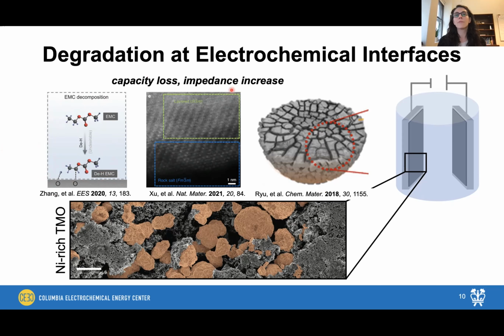We also have a transition from the layered architecture within the active particles to this rock salt-like structure on the surface of the NMC811 that leads to this increased resistance during extended electrochemical cycling. And then you'll actually notice in this SEM image that these are not primary particles, they're actually secondary particles of NMC stuck together.